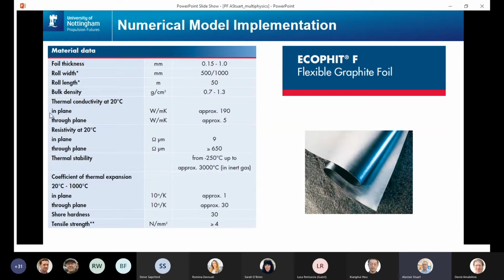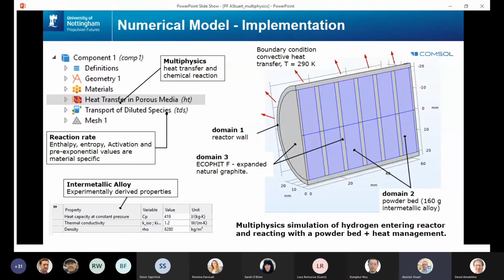The important properties for us at the moment are in the middle. You can see thermal conductivity at 20 degrees. In the plane, it's 190 watts per meter Kelvin, and through the plane, it's 5 watts per meter Kelvin. So I can embed that into the solver now. I can introduce that as a new material, and in the next slide, I'm doing that.